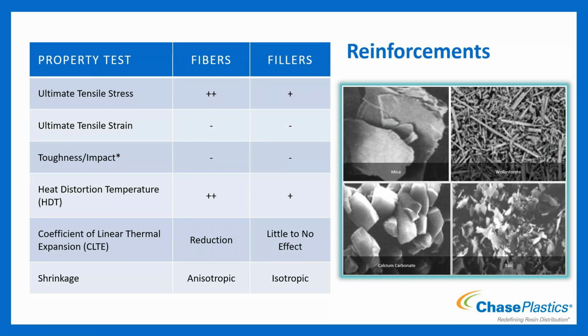And then with shrinkage, you're going to see more anisotropic shrink - isotropic shrink being uniform shrinkage, so in the flow and cross flow direction they'd be uniform. Anisotropic meaning not uniform, so you're going to see more shrinking in the cross flow direction than the flow direction. I have a few graphs to point that out in further slides.